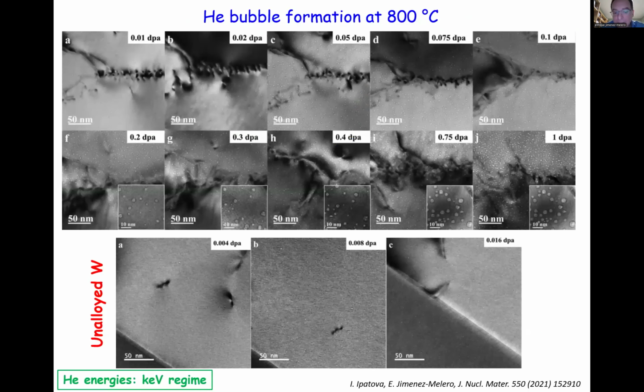Now, if we look at higher energies of helium, or if we look at helium generated inside the material, then we can have helium bubbles as well, not just very close to the surface, but also in the bulk of the component. One way to understand the process is what we did, which is to do transmission electron microscopy in situ in real time while we are exposing the material to, in this case, helium ions that we are implanting.